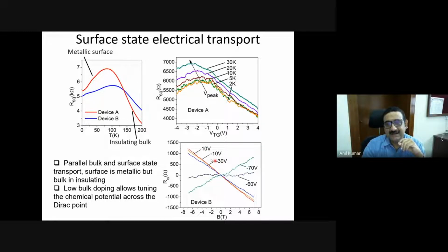Again, you see here, plus 10 volt, minus 10 volt, minus 30 volt, it gives a slope as if this is an N-type conductor. But if I increase the voltage further, and it crosses the charge neutrality point, the nature of the charge carriers changes, and this is the P-type region. So this set of experiments proves that I have a topological insulator crystal.